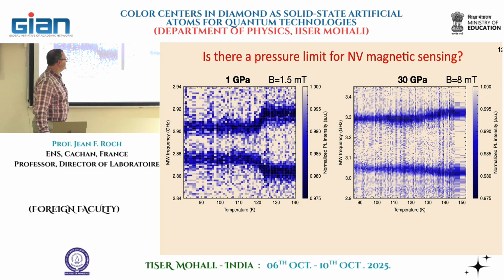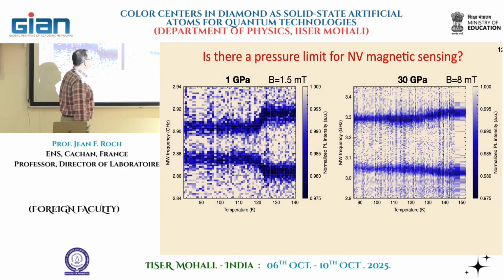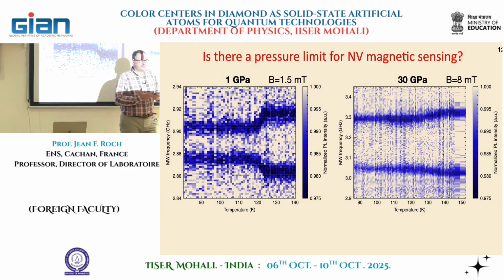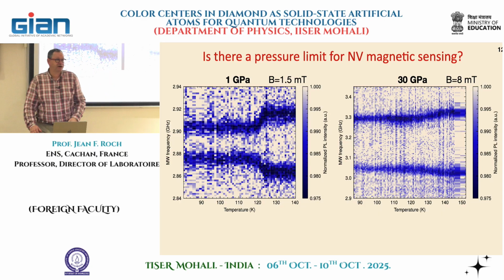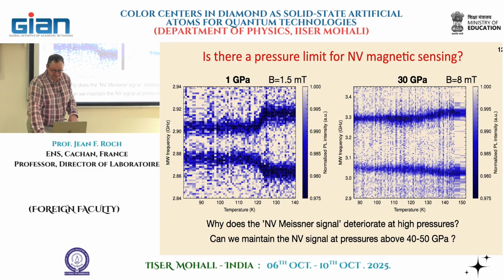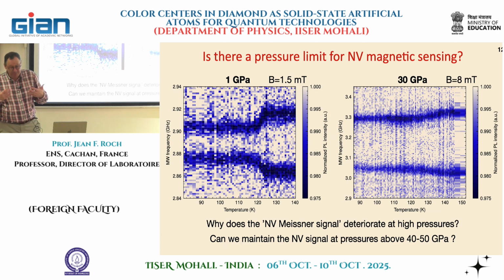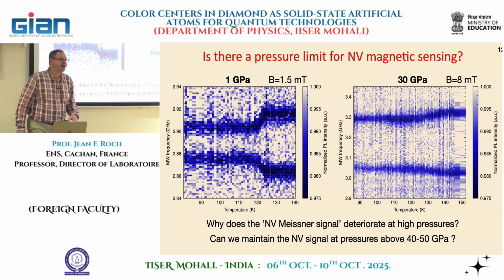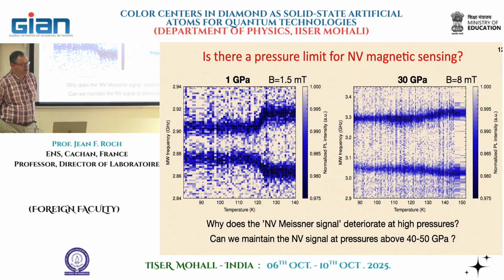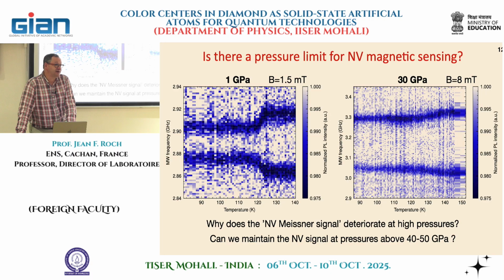You observe that the contrast of the ODMR signal is strongly reduced, up to a point where, if we increase the pressure a little bit more, we cannot see anything. So somehow the NV signal deteriorates with pressure. People thought that this would be a practical limit for NV magnetometry, somewhere around 30 to 40 gigapascal. So the question is, why does the NV Meissner signal deteriorate at high pressure? And can we maintain the signal at pressure above this practical limit?